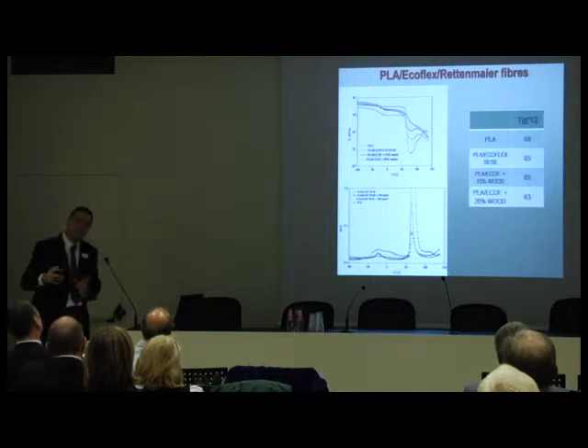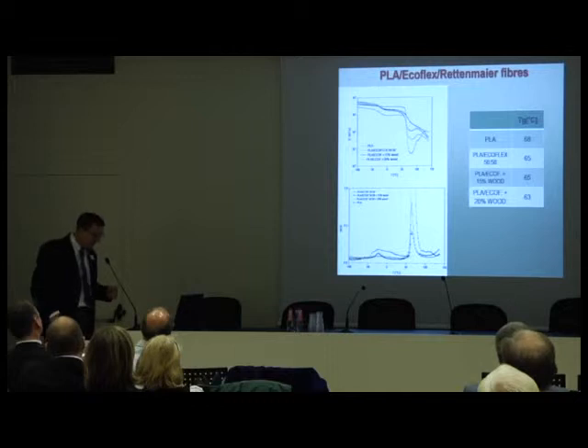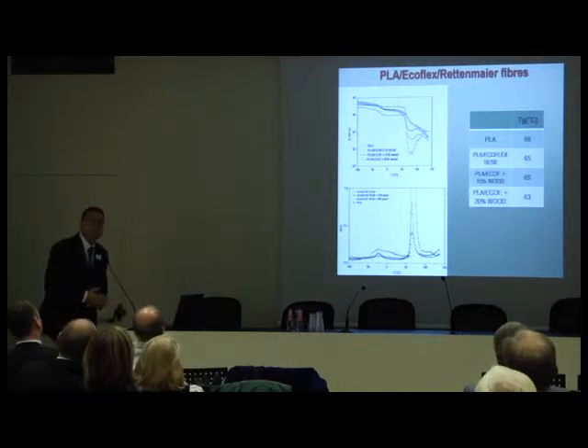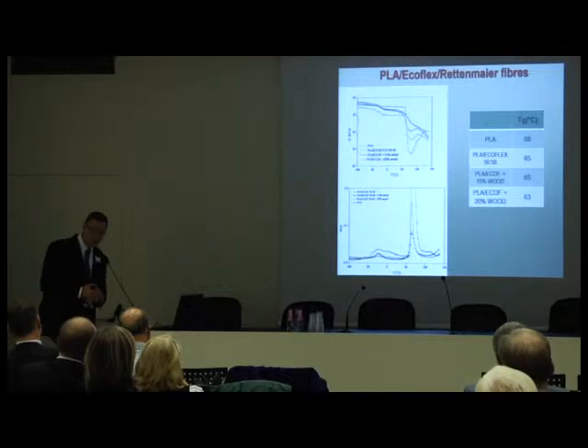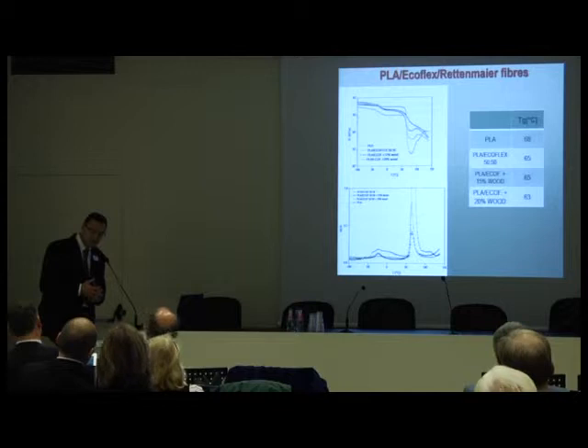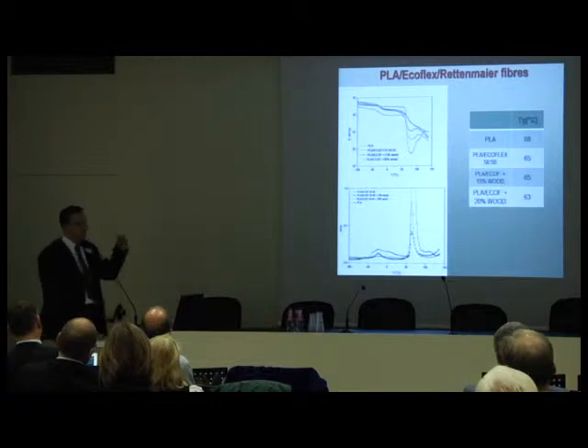This is crystallization, but of course it's not doable under industrial conditions, because crystallization is very long. So we tried with an industrial injection molding machine, and you need some nucleants to try to accelerate the crystallization, but still you need about 90 degrees for the mold, and about 2 minutes of injection molding time. So really it's not practical. So we cannot crystallize the material. It has to be amorphous.